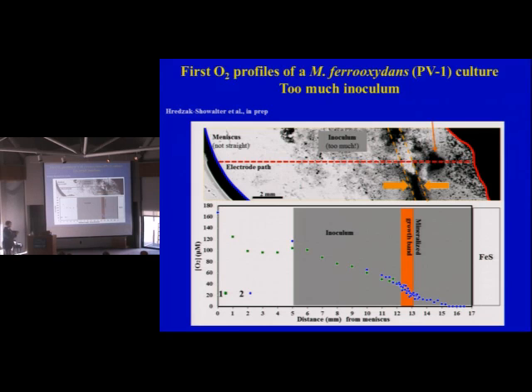You can see a band right here. That's where most of the inoculum was. The electrode path went this direction. This is a 2 millimeter marker here, and then we made measurements about every 1 millimeter until we really got into the gradient.